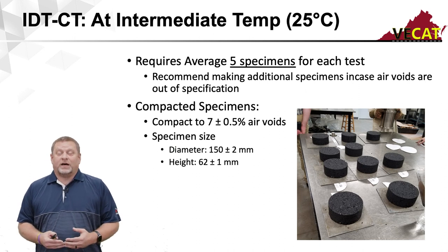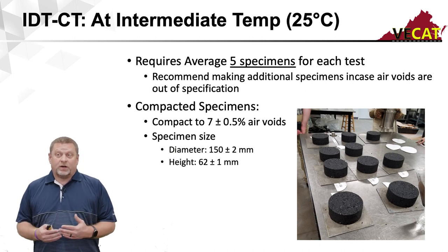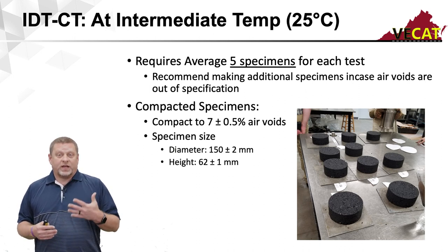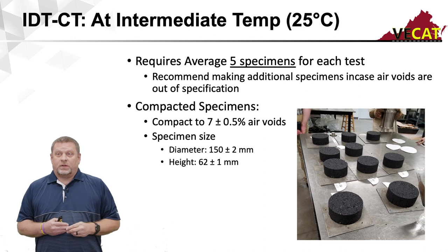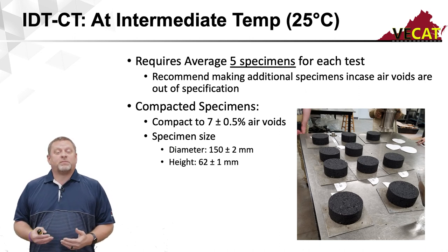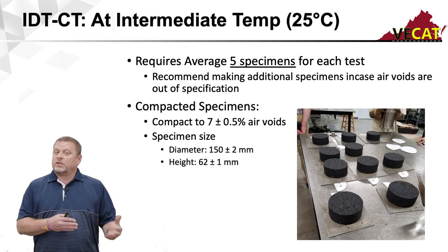Each test value requires an average of 5 specimens. I mentioned that earlier. So you've got to run 5 specimens and average them together to get 1 CT index value. During the design phase, we're going to recommend you make a couple additional specimens instead of limiting yourself at 5. Even though it's a little bit additional work,